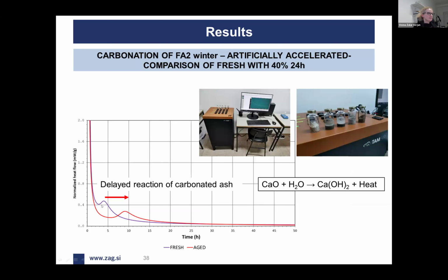Further step was comparison of heat of hydration from the fresh and the one that was the most successfully carbonated. And again, we see the delayed reaction. This is proof that it incorporates at least less lime, less portlandite, and also less some other potentially hydraulic materials or phases. That's why, but still, it does react, at least to a small degree, but it does.